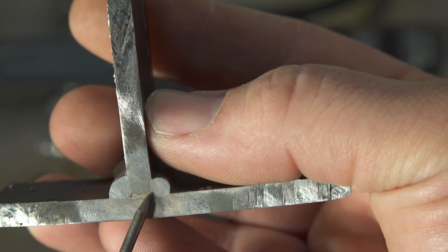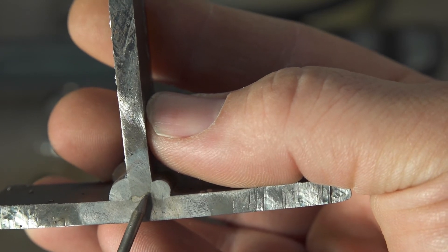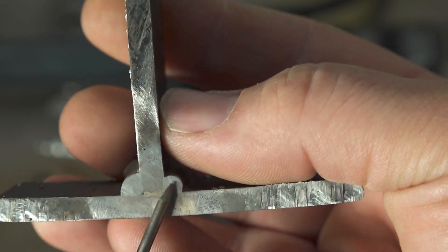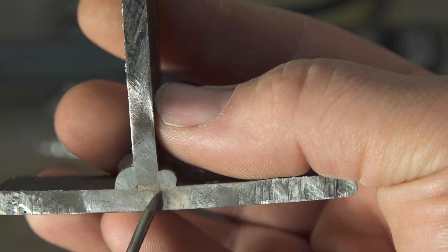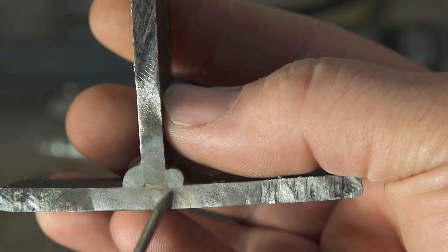Really kind of no tie-in right at the toe, super high crowned bead, not a whole lot of penetration. There's actually a hole down here at the root and then a lid just a very little bit of penetration on this upright portion but really not a lot of penetration. And this was actually the best penetration on 3/16 material I was able to get with the welder in its stock form with AC output.